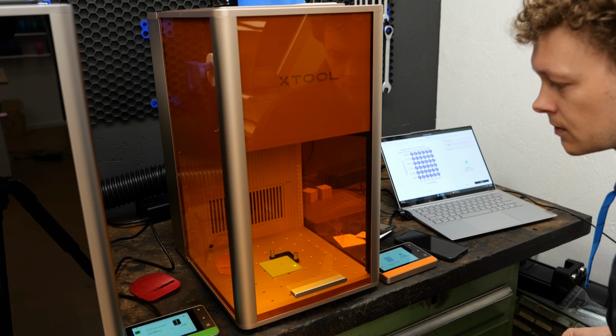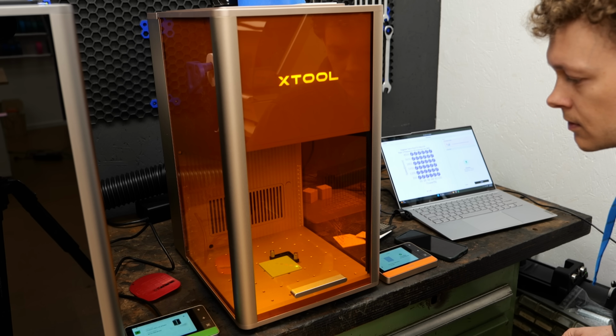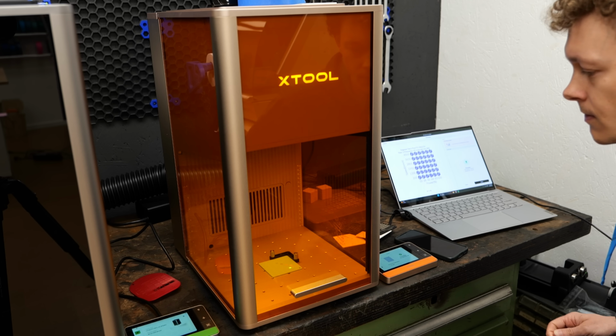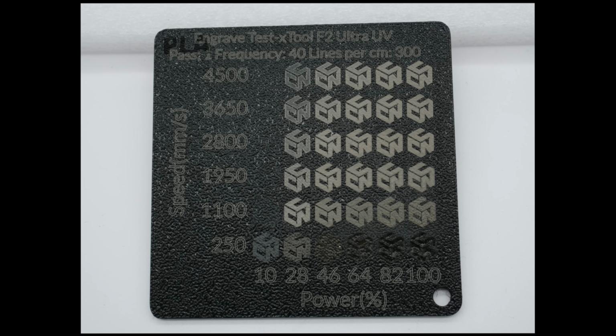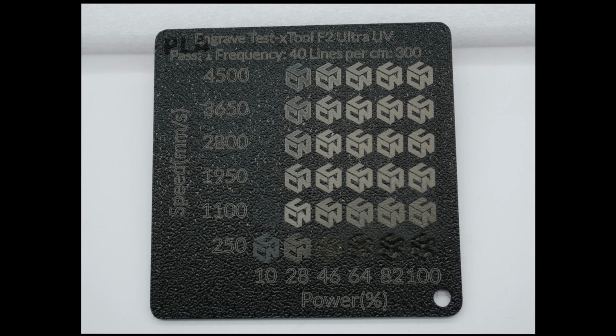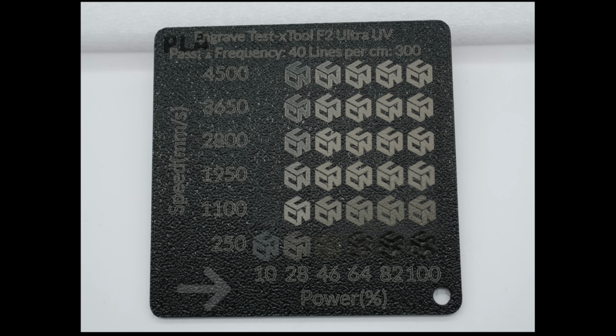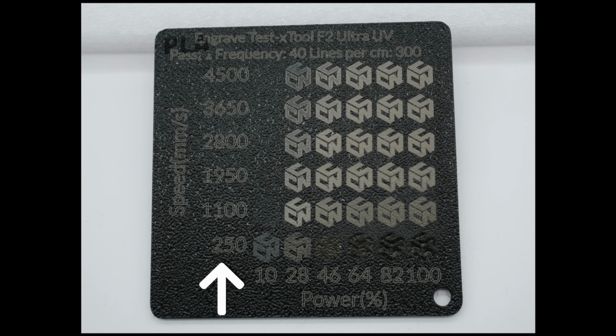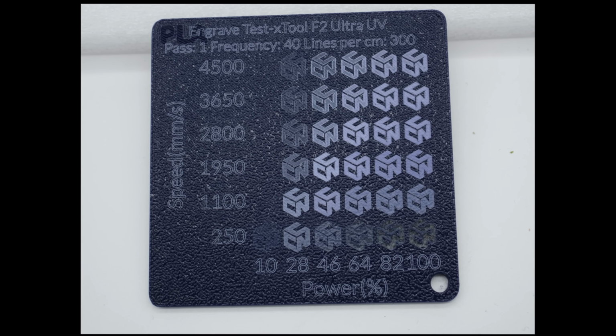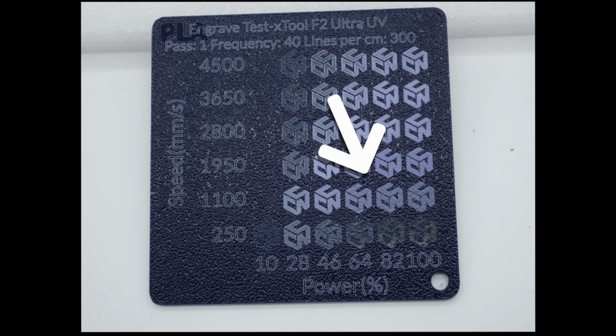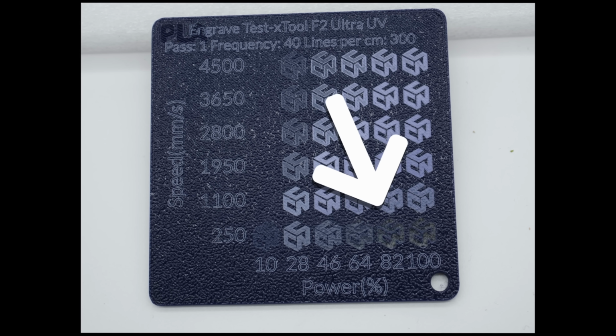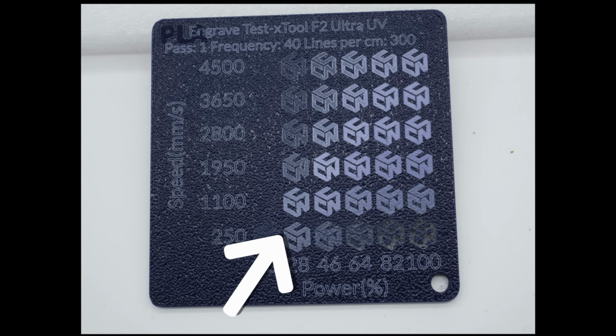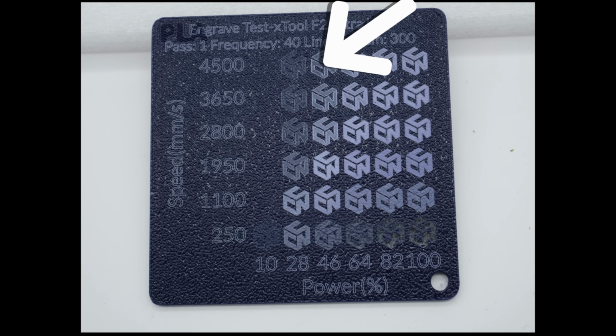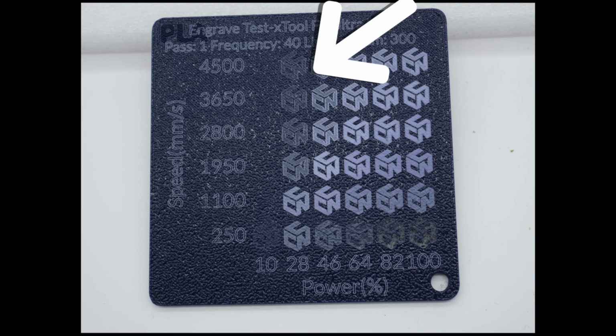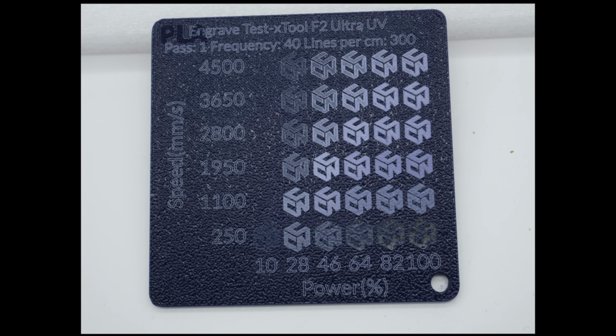I first played around with the settings to get a feeling for the range. The F2 Ultra goes up to 15,000 mm per second in speed, but with the UV laser I noticed that the most interesting changes happened in the lower third of that range. So for most of my test plates I used the range from 10 to 100% of the 5 watt laser power and 250 to 4,500 mm a second travel speed. On many materials, that gave me a very useful gradient. In one corner, the energy input was so high that the material melted, charred, and sometimes even burned. Then there was a band where I got a clean, high contrast mark, and in the opposite corner, the energy input sometimes was so low or the speed so high that barely anything happened anymore.